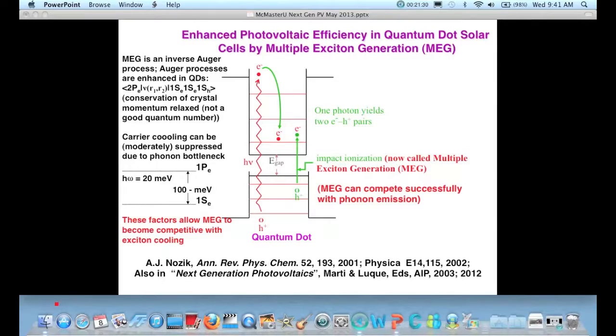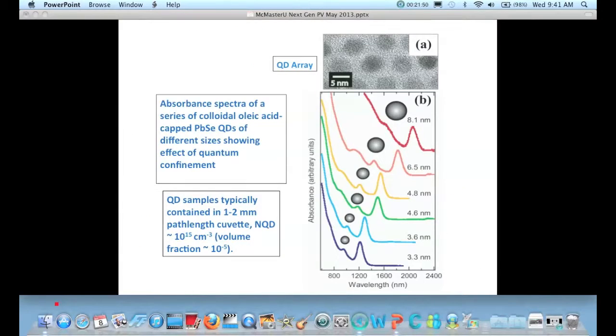These two factors led to a prediction back in, say, 2002 or 2001, that you should have a higher efficiency of multiplying the carrier production from absorbed photons in quantum dots. And as I mentioned, in quantum dots, you can change the band gap just by changing the size. Unlike bulk materials, where to change the band gap, you have to change the material. But in the quantum dot, you keep the material the same, just change its size, and you get very large blue shifts in the absorption, which corresponds to changes in the band gap. And this depends primarily on the effective mass of the material.